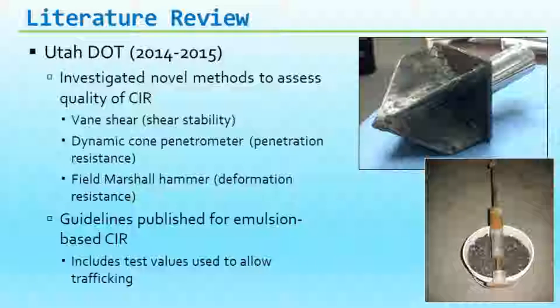They've also been using a dynamic cone penetrometer to measure penetration resistance, getting some good information out of that. They do have some problems with it: if you're going in a relatively thin layer, then you don't get too much information out of it. They're looking at a field Marshall hammer for deformation resistance, so just banging that into the pavement, seeing how far it sinks in.